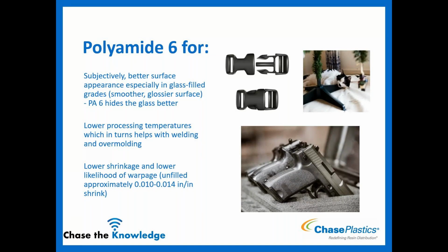And then lastly, another really good point is that it shrinks less. And so you end up with lower likelihood of warpage, warpage being differential shrink, so shrink in different directions being different. You get lower likelihood of that and lower shrinkage in a 6 versus a 6,6. So approximately 10 to 14 thou shrinkage versus your 6,6, which is closer to 20 thou inch per inch shrinkage. So better surface appearance. Again, I say subjectively, if you like it shinier, that's for you. So better surface, lower processing temperatures, which makes it better for secondary operations, and then lower shrinkage and lower likelihood of warping.